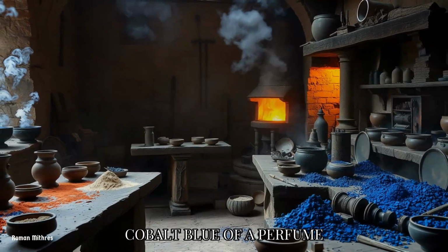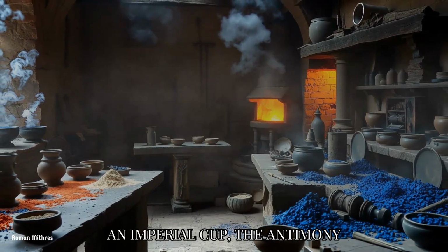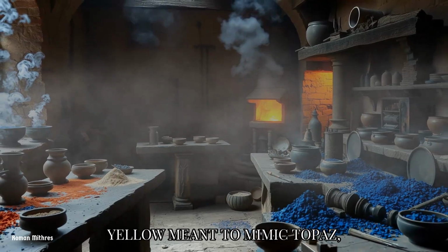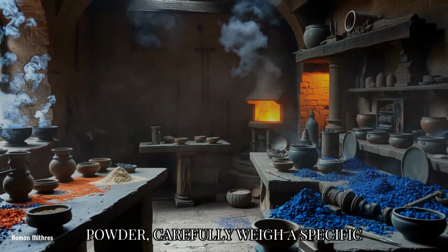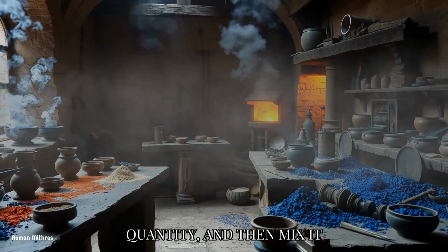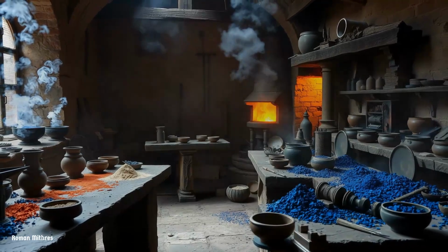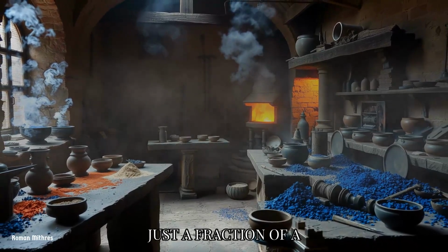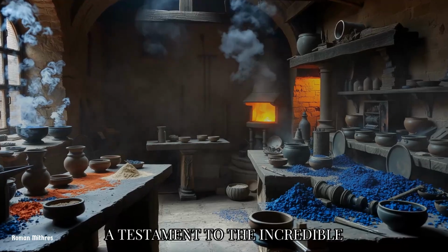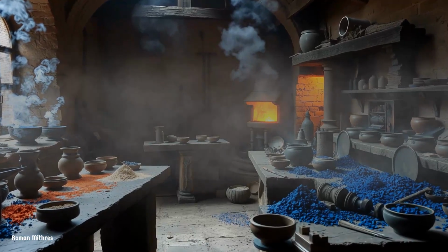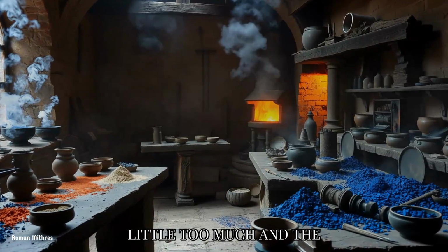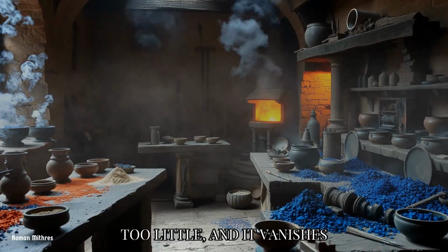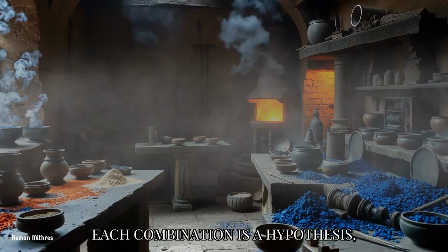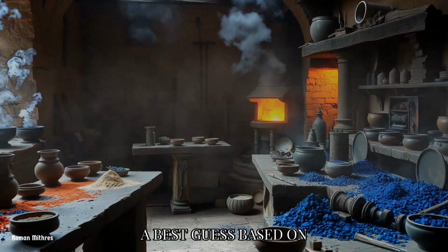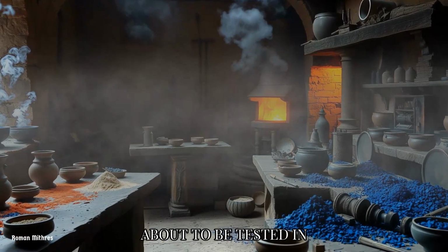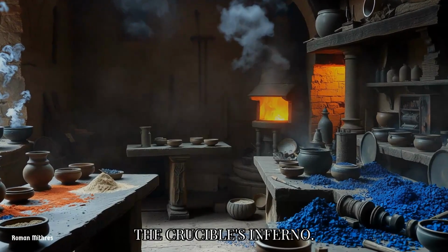For each target hue, the cobalt blue of a perfume jar, the manganese purple of an imperial cup, the antimony yellow meant to mimic topaz, they must first grind the raw mineral into a fine powder, carefully weigh a specific quantity, and then mix it thoroughly into a fresh batch of their fritted base glass. The amounts are tiny, often just a fraction of a percent of the total batch weight, a testament to the incredible potency of these natural colorants. It's a delicate dance. A little too much and the color becomes opaque and muddy, too little and it vanishes into a faint, unsatisfactory tint. Each combination is a hypothesis, a best guess based on archaeological evidence and historical texts, about to be tested in the most unforgiving of courts, the crucible's inferno.